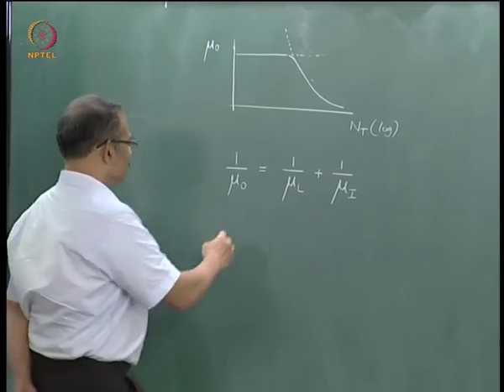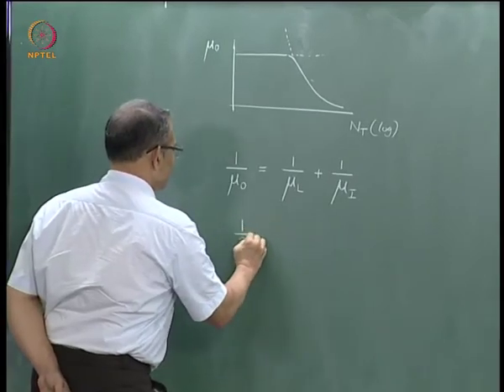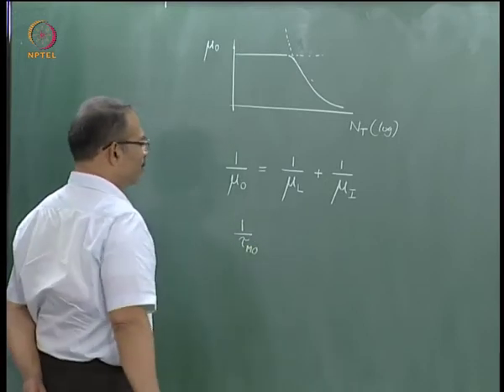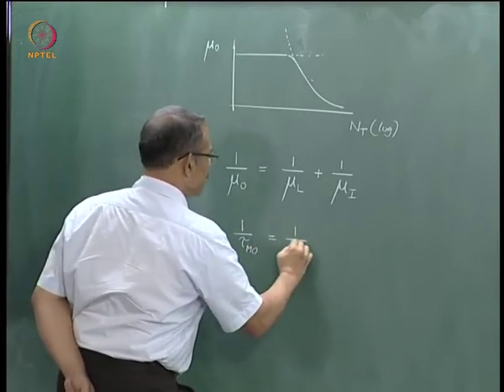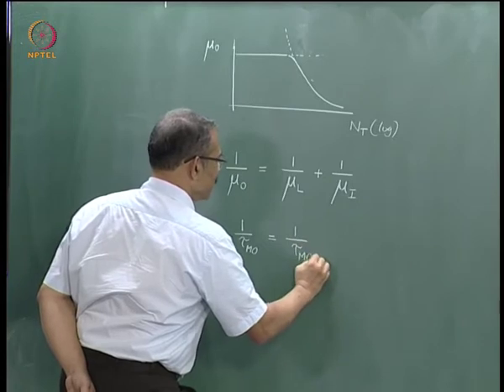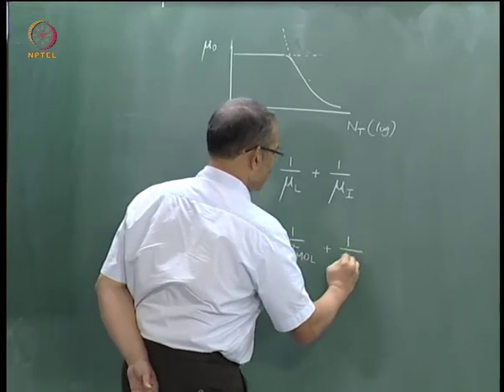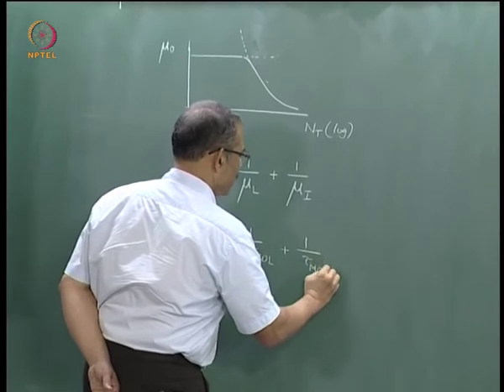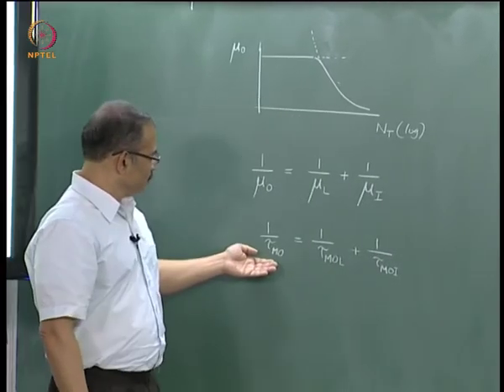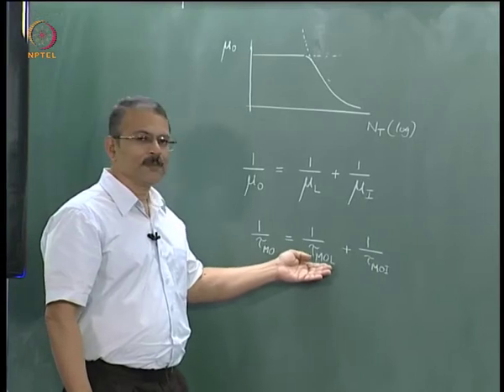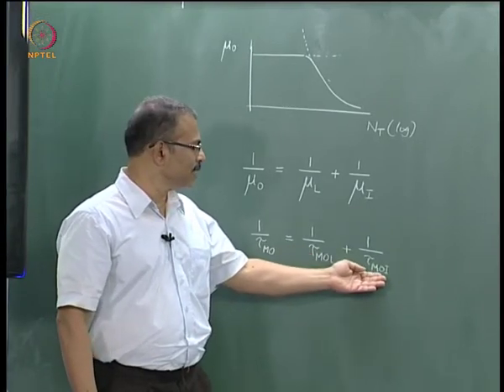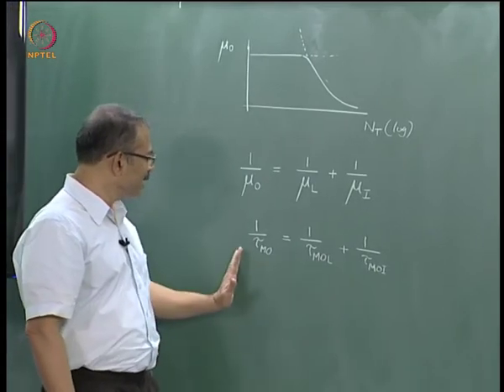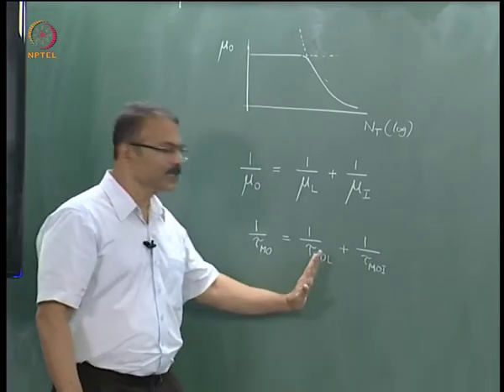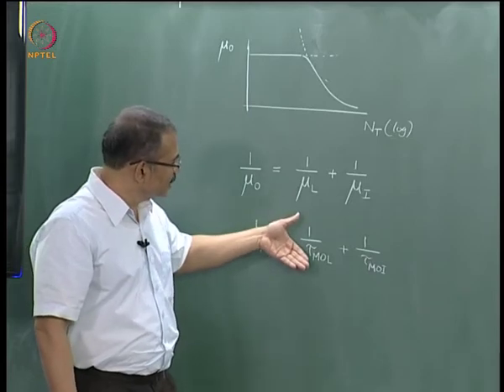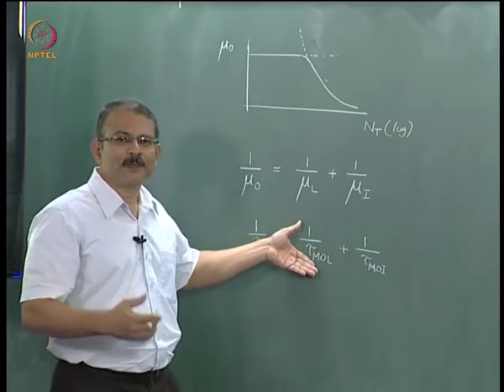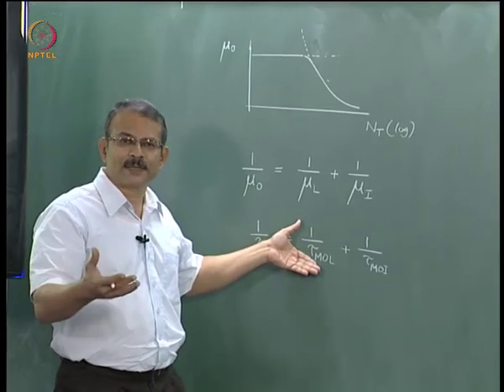Why? Because I can write in terms of the momentum relaxation time 1 by tau m 0 equal to 1 by tau m 0 L plus 1 by tau m 0 I. This is the momentum relaxation time because of lattice scattering, and this is momentum relaxation time because of ionized impurity scattering. Now why can I sum up the reciprocals? Well, it is very simple. 1 by reciprocal of this time represents the number of scattering events or scattering rate.